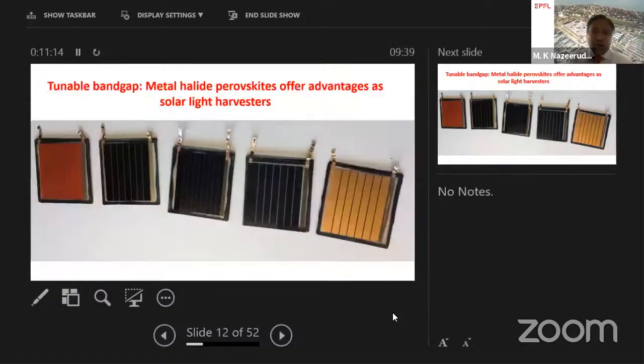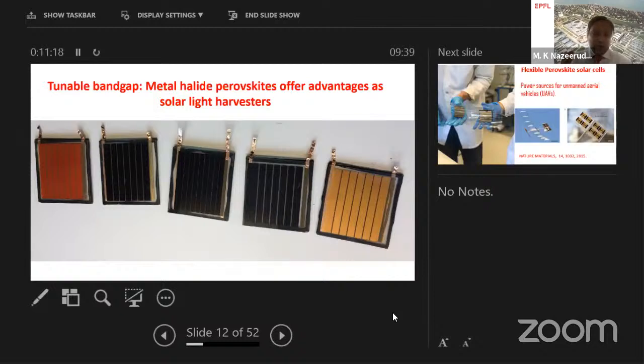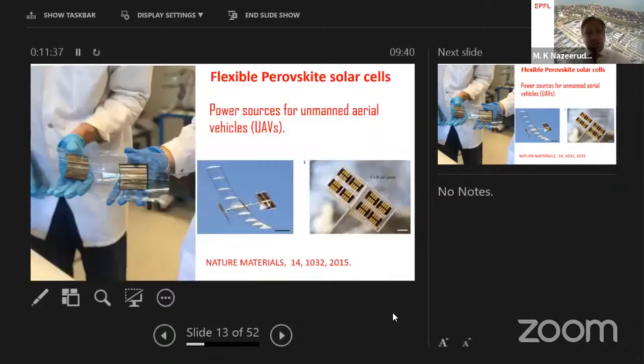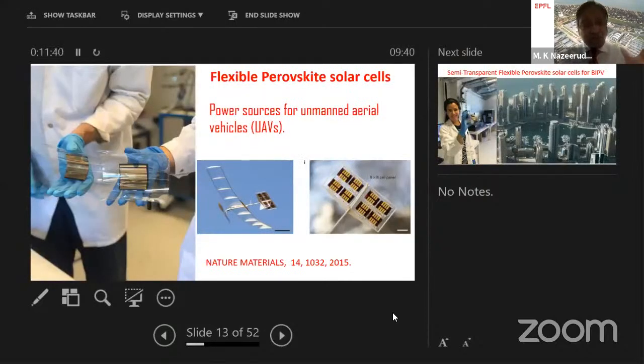The next slide shows you the importance of the tuning properties. Tomorrow, if we want to have differently colored panels, it's possible with the perovskite solar cells. That's not the case with silicon solar cells. Not only can you tune the color of these materials, you can also deposit these perovskite materials on plastic substrates, as shown on the next slide, so that the weight of these perovskite solar cells using plastic as a substrate is extremely low. In other words, the power output versus the weight of the perovskite solar cells is very high. This is the highest power output with respect to the weight of perovskite solar cells available today on Earth.